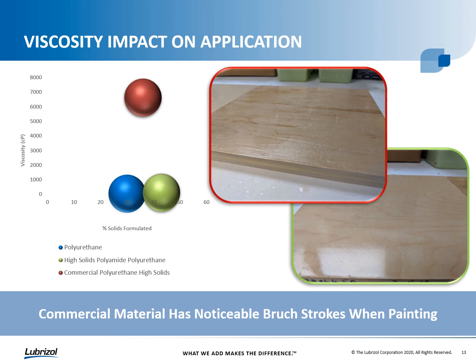Whereas in the bottom picture, we have the high solids polyamide-based polyurethane material that was formulated up over 40% solids, but maintained its low viscosity. And we can see a very nice uniform appearance, very high gloss, good clarity, and a very desirable appearance.